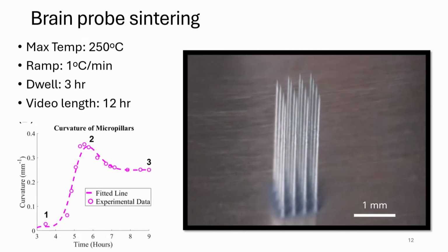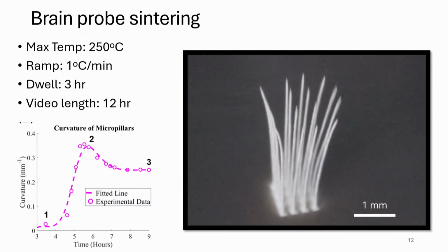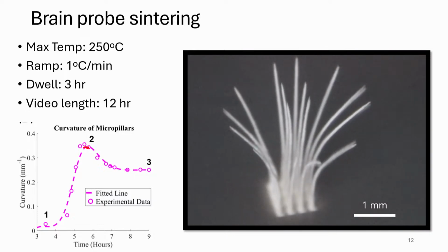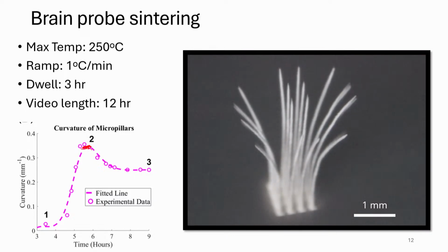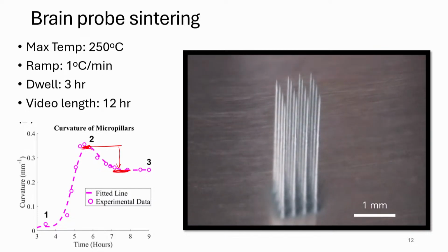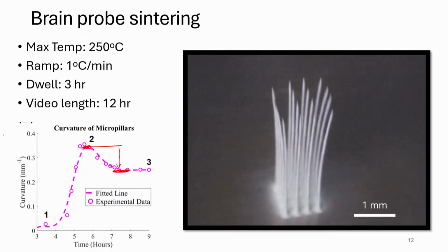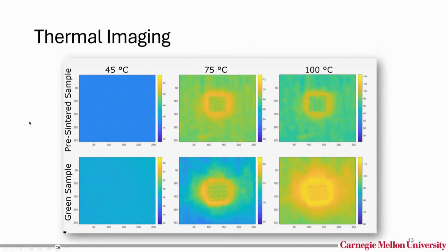So if you look at the curvature, the time history of curvature looks like this. You get a peak curvature. This is a temporary curvature, and then you have a final curvature, which is never corrected. Now, the first thing we have observed here is that temperature is higher on the outside.